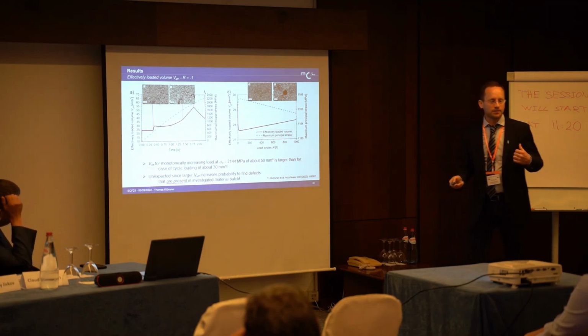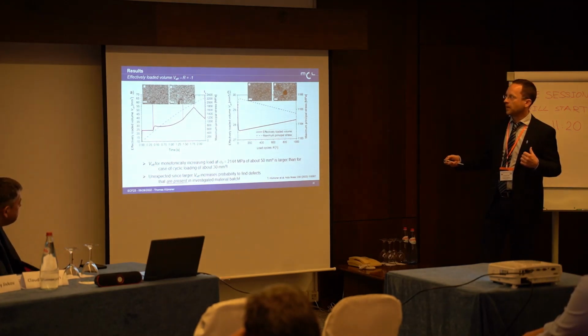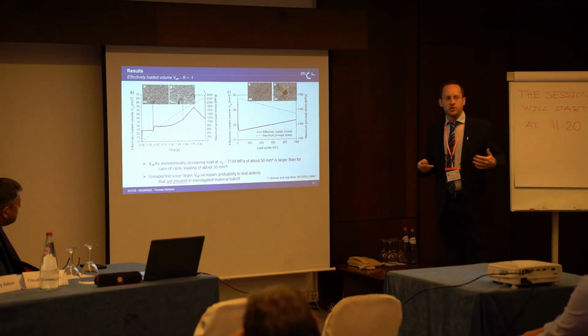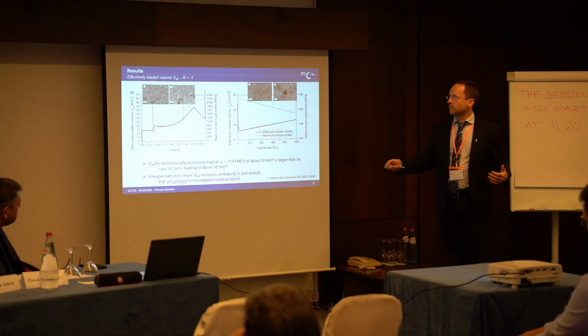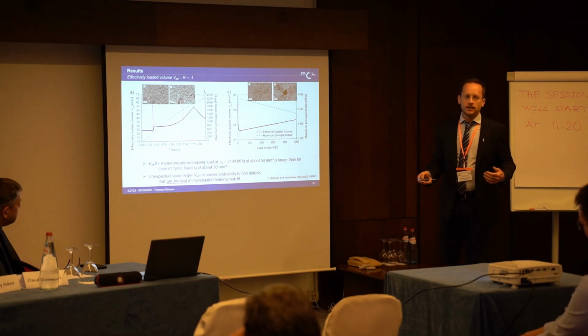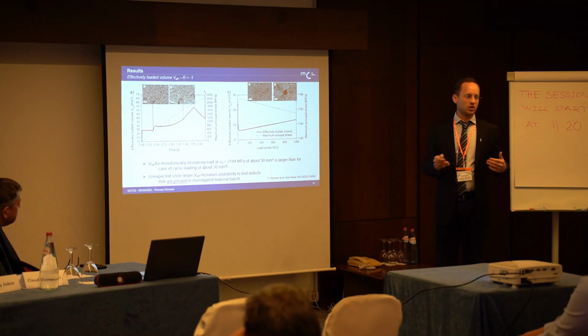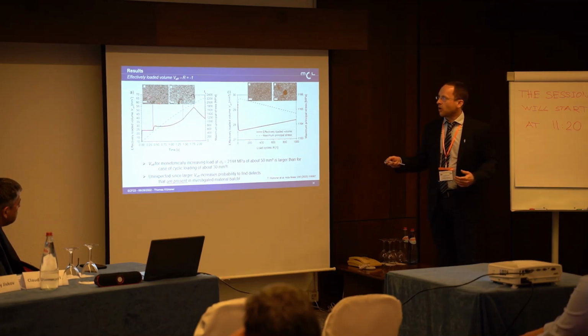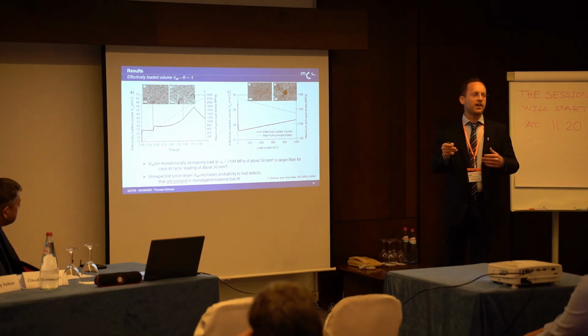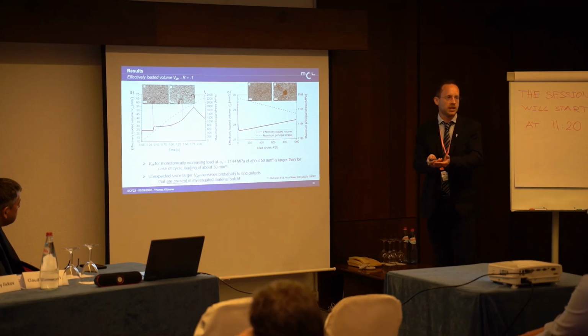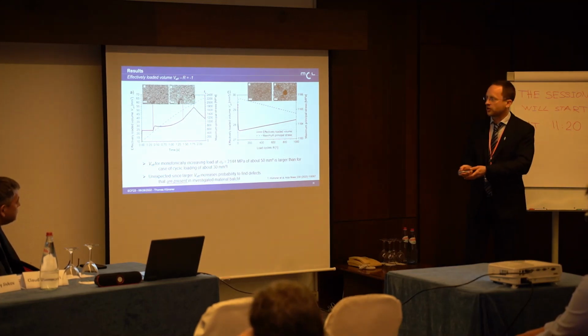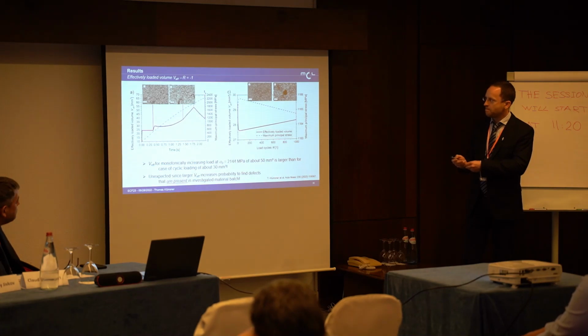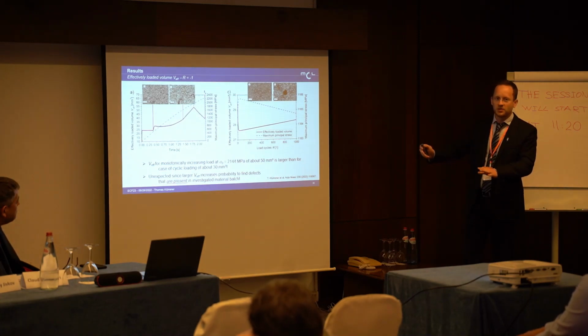But this is not the case, and I think the reason why you find only the above average size tungsten carbide grains in those cases with monotonically increasing load is that tertiary creep happens close to the fracture stress, and that's why small variations in the binder content or above average size tungsten carbide grain zones in the sample become then the most dangerous spot in the specimen to fracture. And this is, I hope I could convince you, that